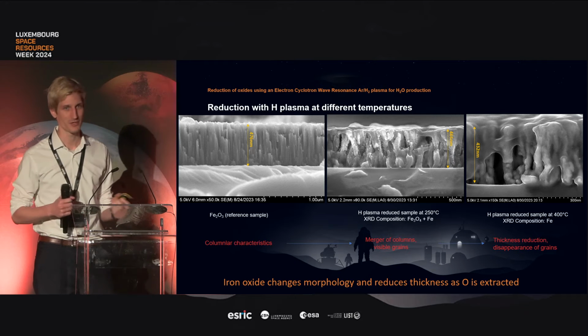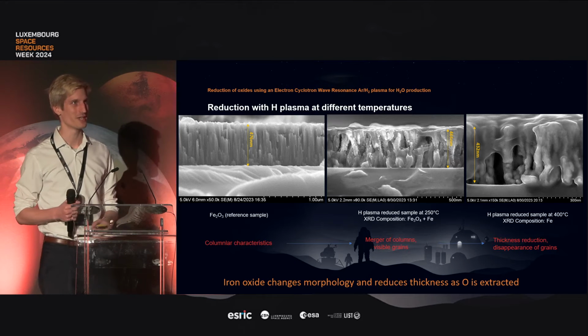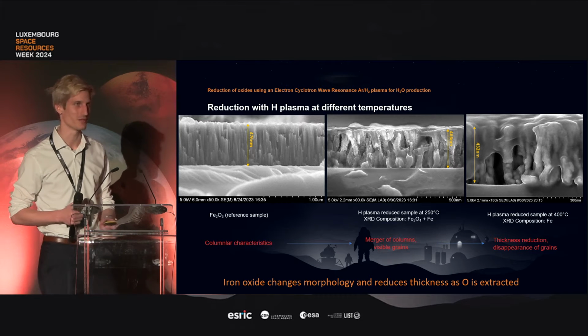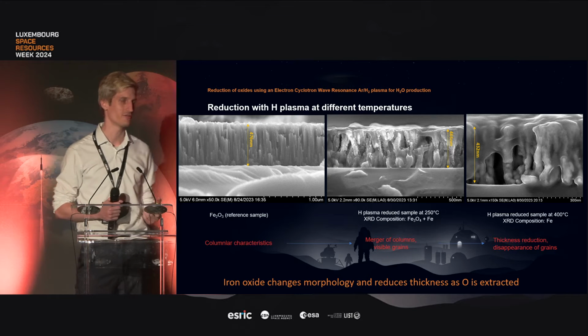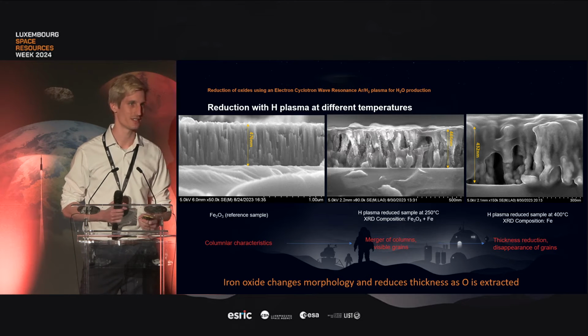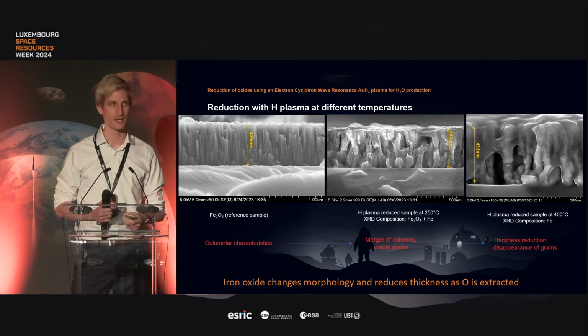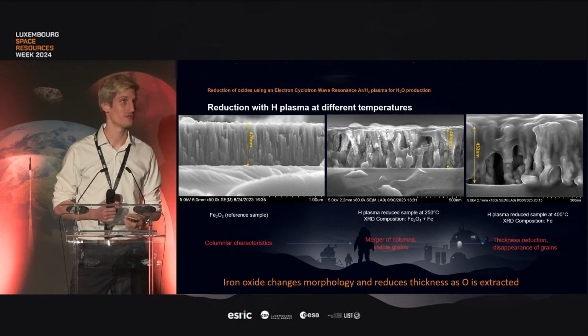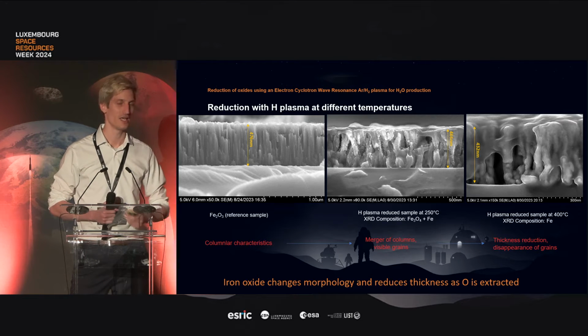Now let's get more visual. How does the material look before and after the reduction with hydrogen plasma? On the left, we have the reference sample. It's a cross-section, a SEM image, and we see classical columnar growth. We see these columns of Fe2O3, of iron oxide.